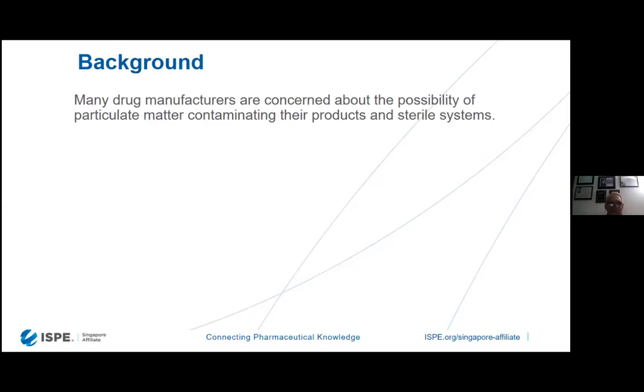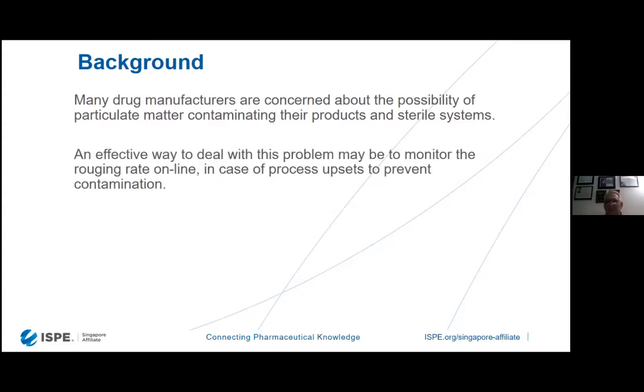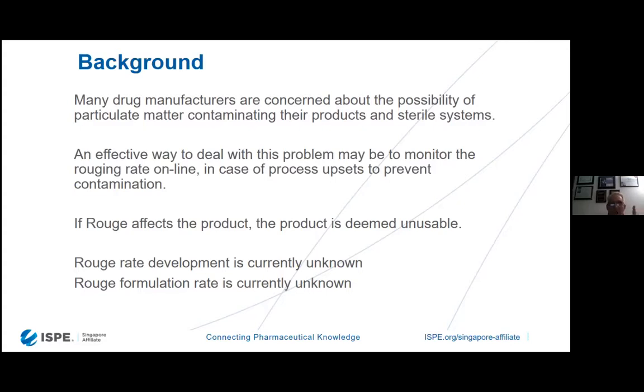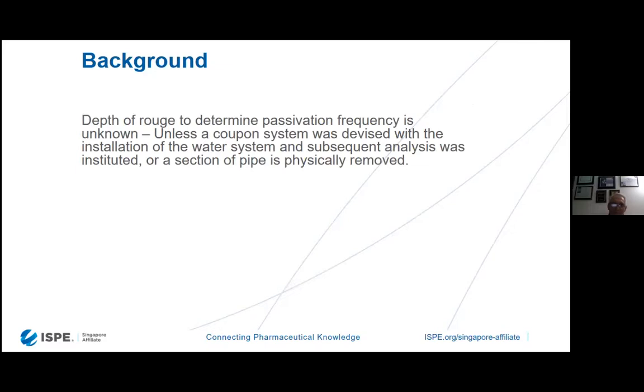Many drug manufacturers are concerned about the possibility of particulate matter contaminating their products in sterile systems. An effective way to deal with this problem may be to monitor the rouge rate online, and in case of process upsets, to prevent the contamination from causing a process upset, which is probably more effective. If rouge does affect the product, though, the product is deemed unusable. Currently, in most sites, rouge rate development is unknown, and the formation rate is unknown because there's no way to monitor it.